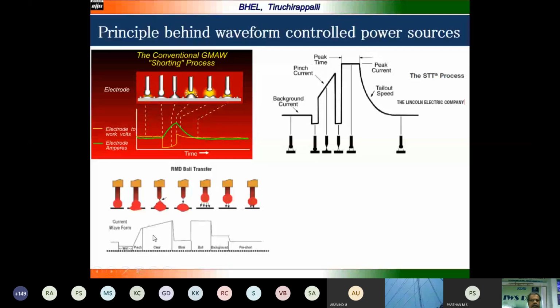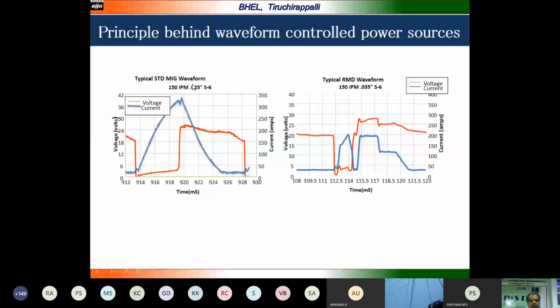It's a typical STD MIG waveform where you can see the current and the voltage here, and here you can see how low the current is. Actually, the welding can be done with half of the current, and because of this the RMD waveform is shown here. Because of that low heat input, these processes are widely used now. A conventional CO2 process produces more spatter, and with STT the spatter is very little or almost minimal.